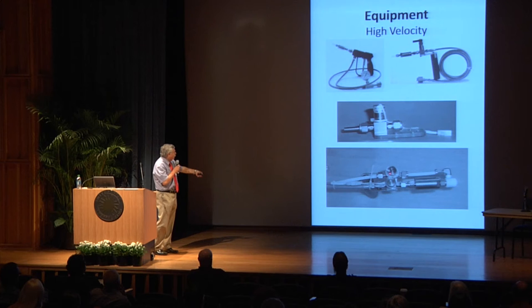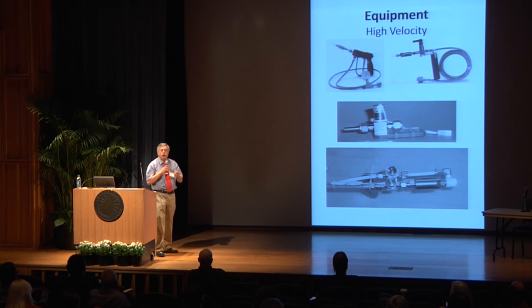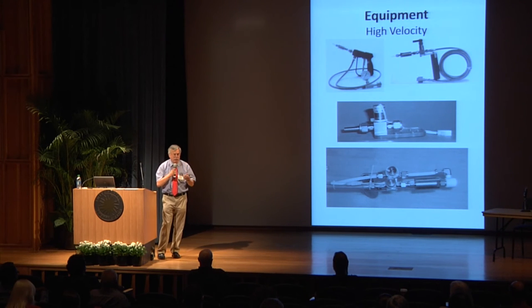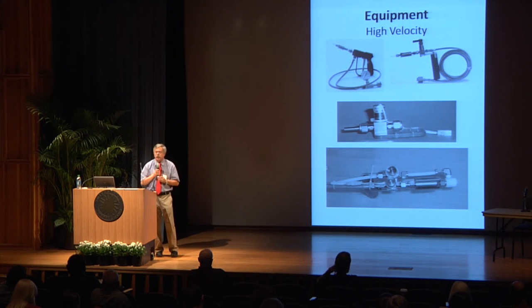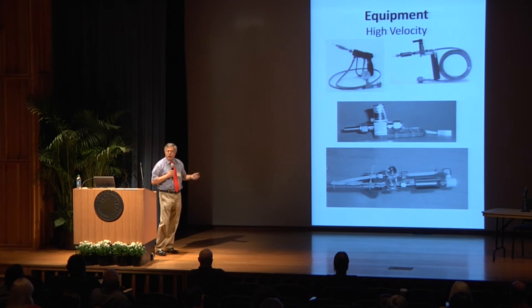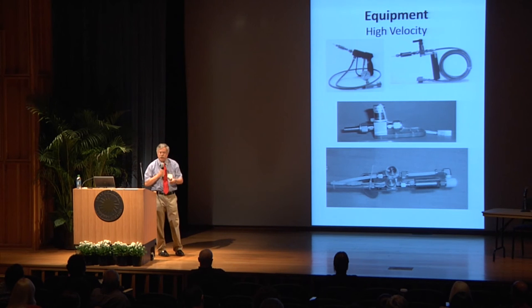Down here, this is two solenoids here, and what this is, we call this a dual gas unit. The CO2 enters through this line, goes through this solenoid, and out the nozzle. This line here carries nitrogen and goes into what I call my dual gas nozzle, which is a small polymer structure that has 8 ports around the CO2 stream. And you will be talking about using this to clean a polymer-based object. And this is a way of getting around some of the condensation issues.